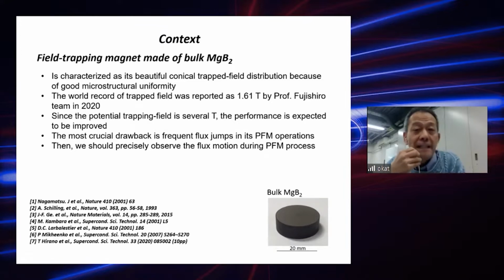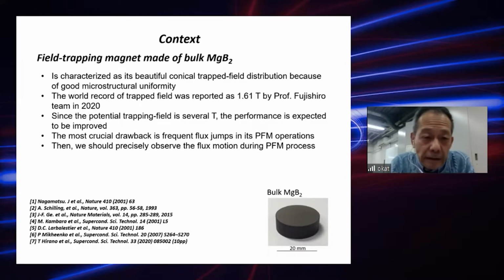In this context, the flux trapping magnet made of bulk magnesium diboride is characterized by its very beautiful conical trapped field distribution, because of the very nice microstructural uniformity of the material. The world record of the trapped field was reported as 1.61 Tesla by Professor Fujishiro's team last year. But since the potential trapped field is several Tesla as reported, the performance is expected to be improved further.